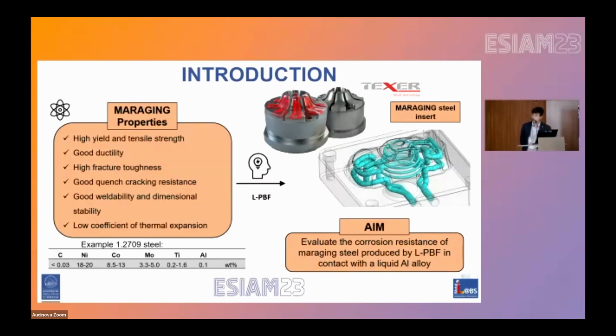Furthermore, the low carbon content enhances the dimensional stability of the alloy that, together with the low coefficient of thermal expansion, makes them easily weldable and so easily processable via the L-PBF technique. Indeed, this technique was recently adopted in the molding and tooling industry to produce inserts with conformal cooling channels capable of improving the productivity. These components usually undergo severe stress conditions and suffer from corrosion due to the contact with the molten aluminum when no protective layers are employed or where this layer is damaged by wear.